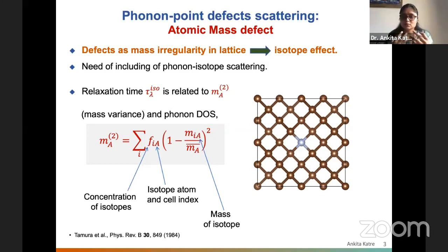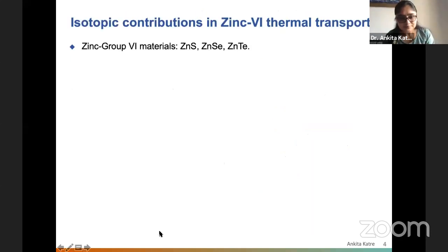So the mass variance not only depends on the mass, but also on the concentration of the defect, which makes complete sense. On the whole, this mass variance goes into the relaxation time, and the phonon density of states also has a huge impact on the calculations of this phonon isotope scattering. You can find how it comes about in the formulation in this paper by Tamura.